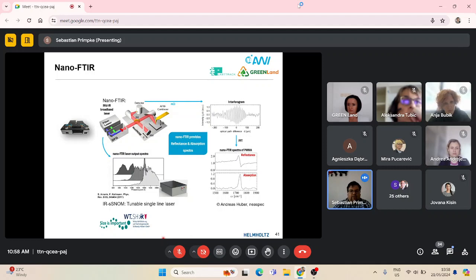It can use two different modes. We have a laser giving our signal to the sample, which is linked to an AFM tip, and then we yield a spectrum, which we can then transform. Or we can use a broad laser and then tune the differences. With this, we are really able to distinguish, for example,